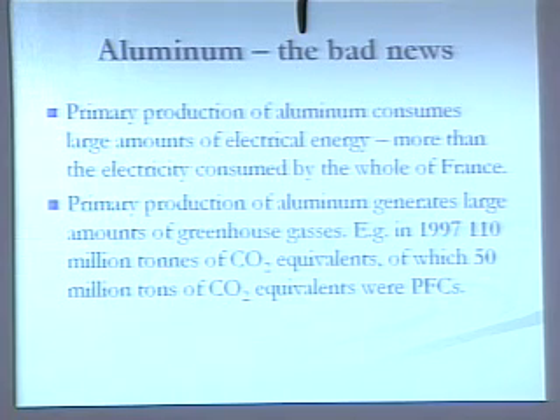So for every ton of aluminum we produce 1.25 tons of carbon dioxide. And worse than that, we also emit fluorides in the production of aluminum. In fact, those fluorides are fluorinated carbons, PFCs as they're known, and they are between 1,000 and 10,000 times worse than carbon dioxide when it comes to global warming.